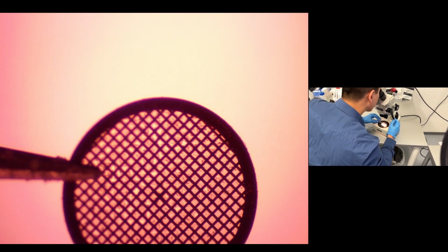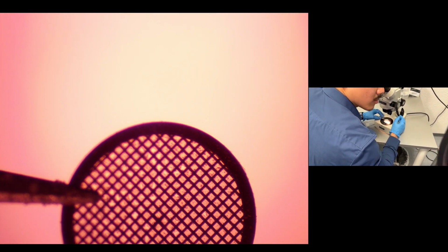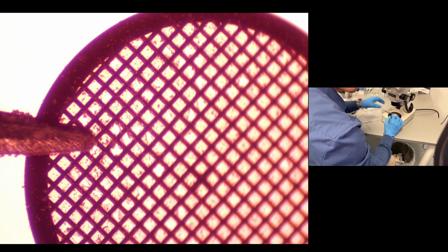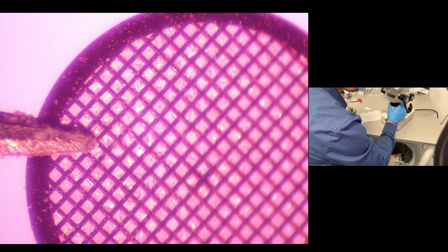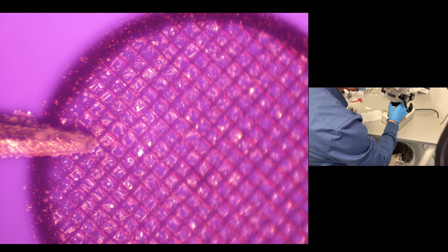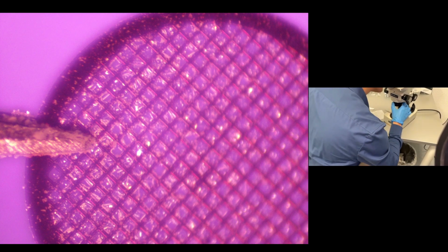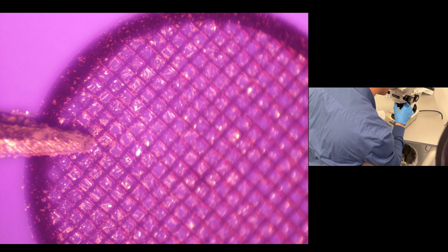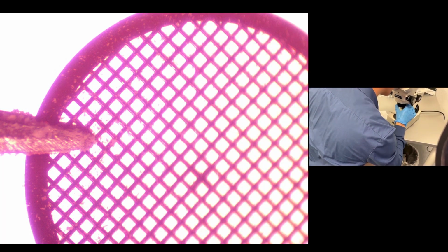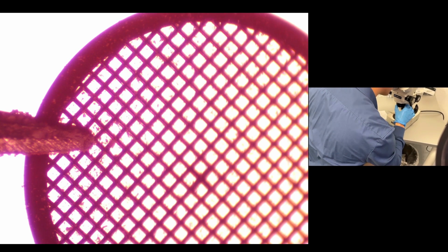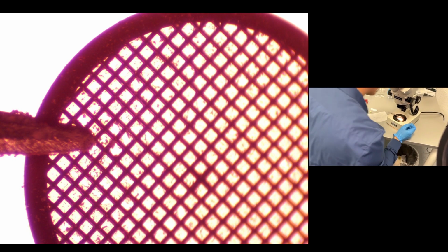Switch to this view here. So you should now see a close-up of this grid. You see this carbon foil, which at some point is a bit ripped, but it doesn't matter, suspended on a copper mesh. Each of those mesh squares is a bit more than 100 microns edge length. And what's important to note is that these little specks of dust are some crystallites, and the ones that you see are in fact already too big to be measured by electron diffraction, but it's still helpful to just assess if the loading density across the grid is reasonable, and to me it looks quite okay.